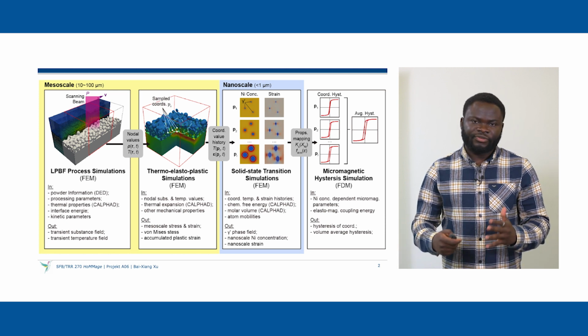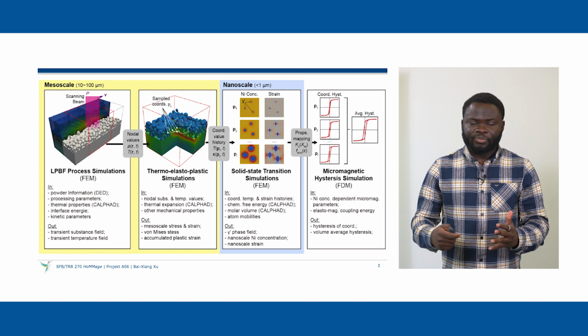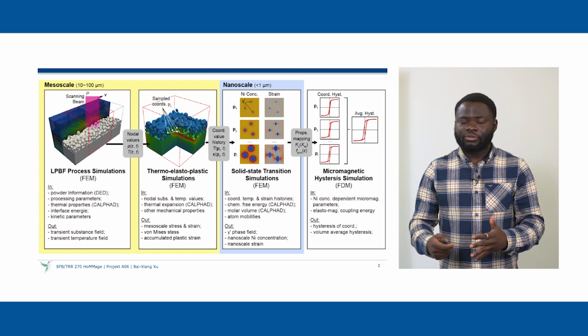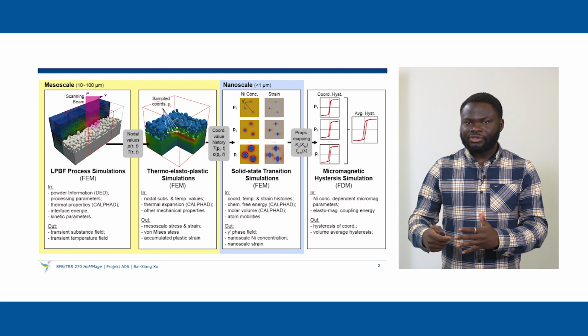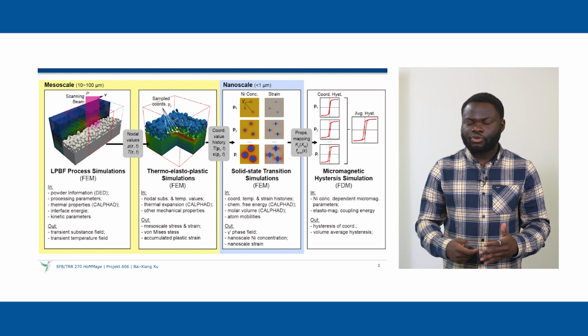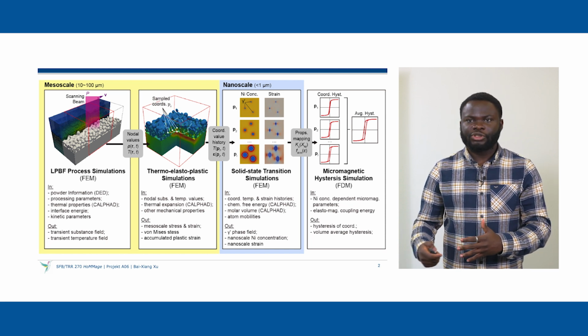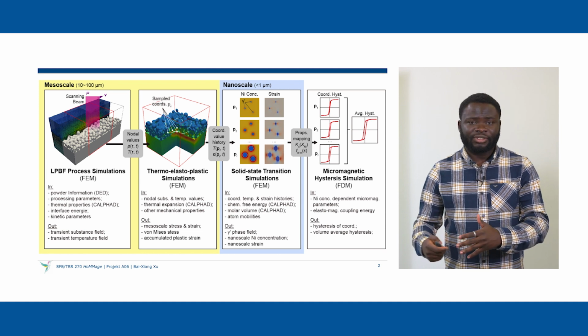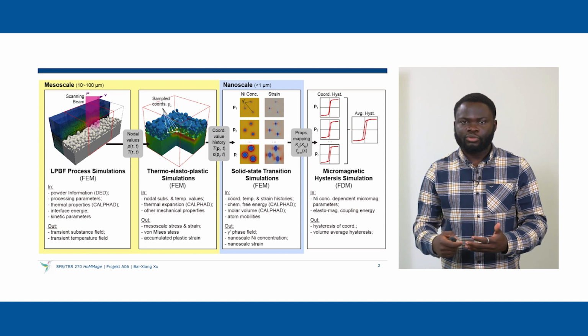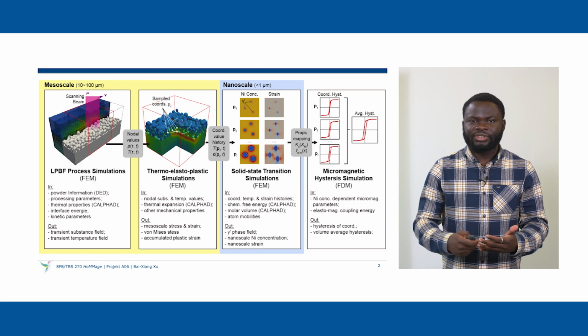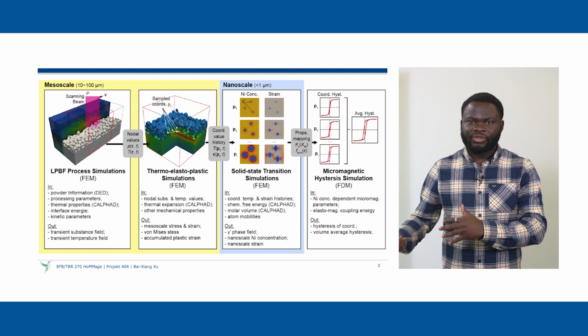Also, we have solid-state phase transition, for example, for specific materials such as iron nickel, where you have a gamma to gamma dash phase transition. Lastly, we also conduct micromagnetic simulations where we obtain magnetic hysteresis at each point in our sample, and we take an average of these hysteresis as the average hysteresis of our sample.